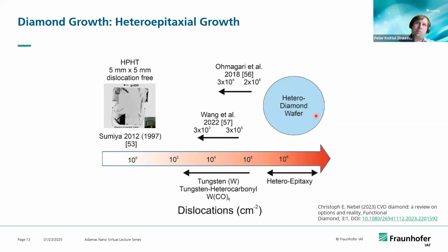That means that most probably due to the merging of these oriented grains, you incorporate lots of dislocation defects and other crystalline defects into the wafer that makes them at the moment not usable, especially for electronic applications. For quantum applications, there is still maybe a chance that even at higher amounts of dislocations or crystalline defects, you may use them. But if you want to use the best material that is available, people still use these single crystalline wafers that are produced basically either by high pressure, high temperature growth or by CVD growth on these high pressure, high temperature substrates.